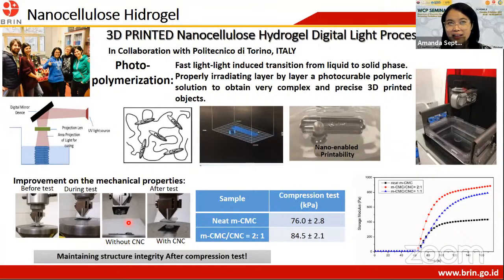The third nanocellulose hydrogel that we are developing is in collaboration, and currently I'm here to continue the collaboration that has been established since 2019. This is my second visit, and we collaborate with the research group at Politecnico di Torino to develop hydrogel using digital light processing. Digital light processing is basically photopolymerization, where we put some photocurable polymers in our hydrogel. Then by using DLP, it irradiates the hydrogel layer by layer to obtain very complex and precise 3D printed objects.